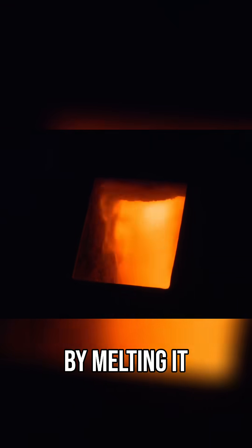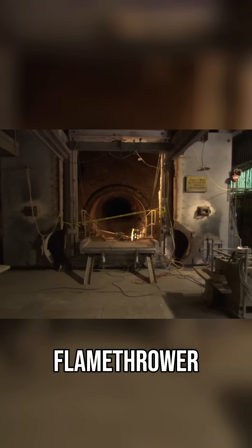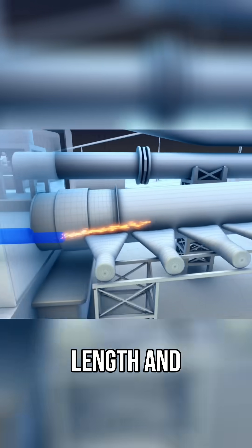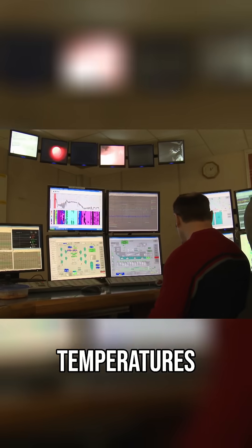Next, you need to bond the dust back together by melting it in this kiln. At one end, a giant flamethrower slides between two blast-proof doors. Fuel blows down its length and explodes into flames 10 meters long. Hundreds of air compressors stoke the fire with blasts of oxygen. Advanced thermal imaging cameras keep constant watch. Temperatures have to be kept steady to make sure the product is consistent — and that's just one of the problems of maintaining a blaze this powerful in a kiln this big.